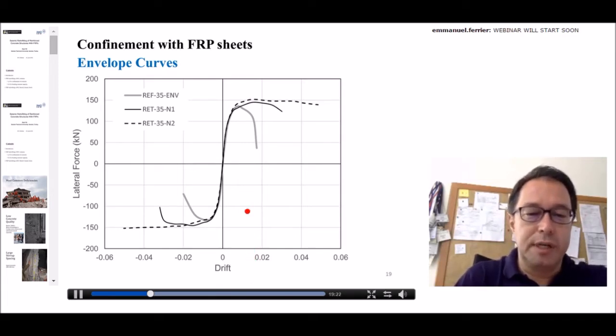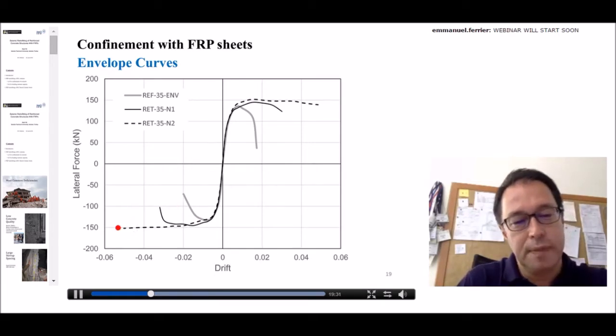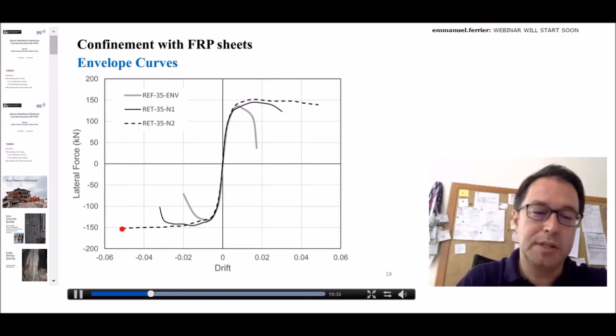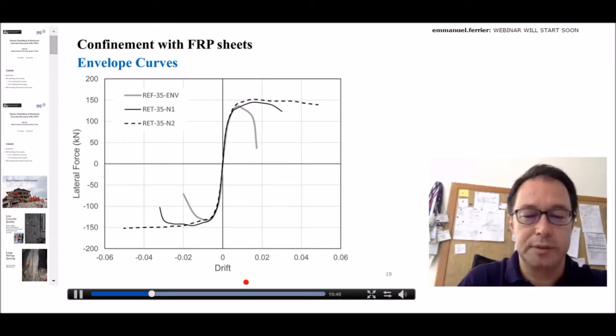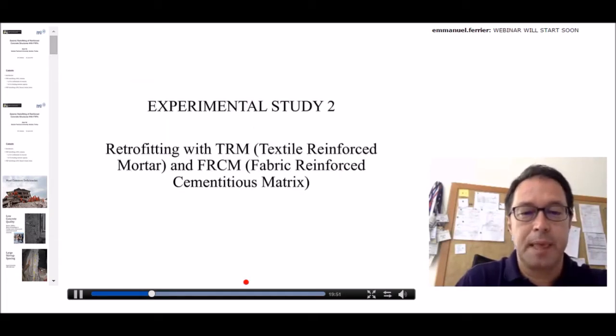And if you look at the envelope curves of these three specimens, you can notice the very significant enhancement in the behavior. But I should say that, of course, this horizontal curve could be misleading. Don't forget that this specimen also lost its strength at around this point. Anyway, we had the failure, but the failure was much retarded in case of the column with two plies of FRP jacket.